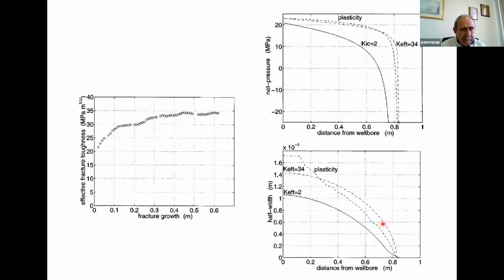In this case here, we don't have a good match as before. The plasticity is narrower near the tip. The reason is that the model we used was full dilatancy. Full dilatancy means that the dilation angle in the plasticity model was equal to the friction angle. In reality, the dilation is lower than the friction angle. So if we have plasticity with dilation lower than the friction angle, non-associative plasticity as we call it, I believe the result will be closer.